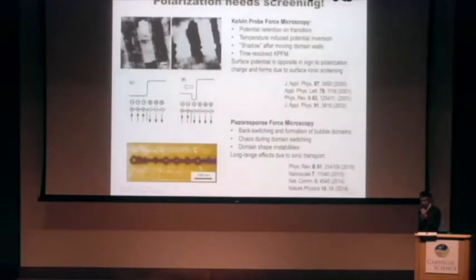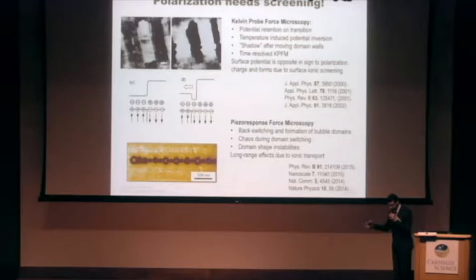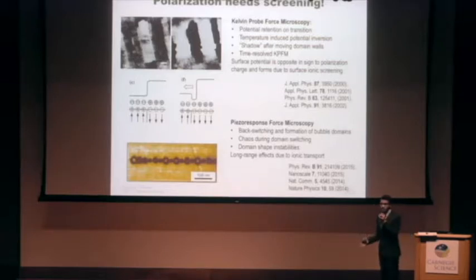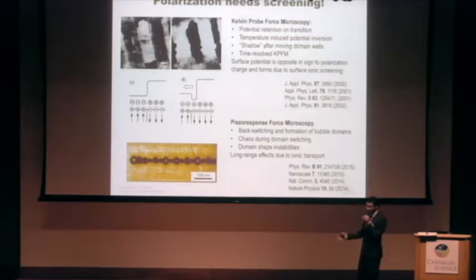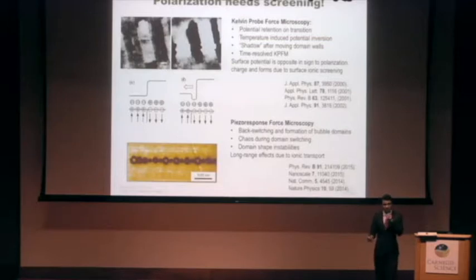One of the major things that has been appreciated in literature, but more or less people have not thought about that much, is that polarization, in order for it to be stable, obviously requires screening, right? So if you have a ferroelectric surface, and you don't have screening, then what's going to happen? Generally, if you're in ambient conditions, you're going to have species that can screen the polarization. In the absence of that, the surface is going to somehow reconstruct, because the bulk obviously wants to stay ferroelectric, so if the bulk is quite large, the energies are going to be quite large, and the surface really has to follow the bulk.